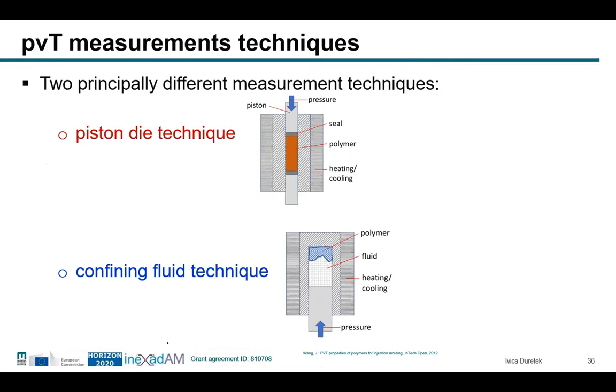For the measurement of the specific volume as a function of temperature and pressure, there exist principally two different measurement techniques. One is the so-called piston die technique. That means the polymer will be compressed with a movable upper piston, and with the upper piston we can build up different pressures. With increasing pressure, the machine can measure the change in the height of the sample, and using the known mass of the polymer and the known volume, it's very easy to calculate the specific volume at different temperatures and pressures. The other method is the so-called fluid technique.